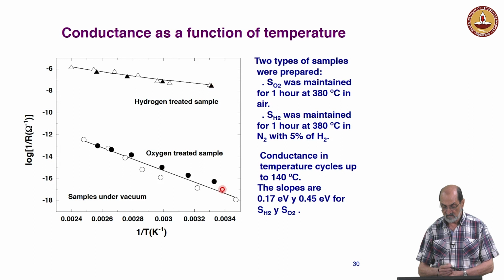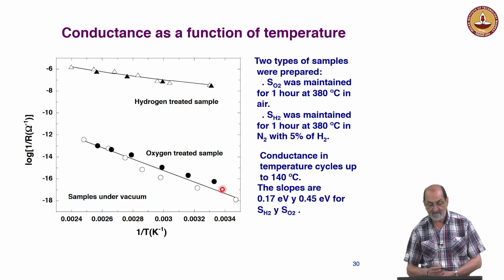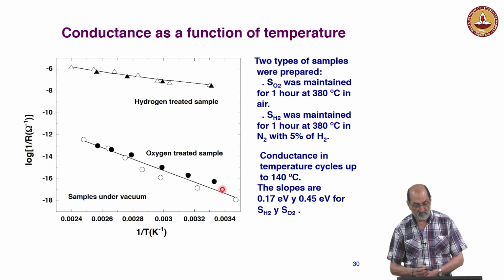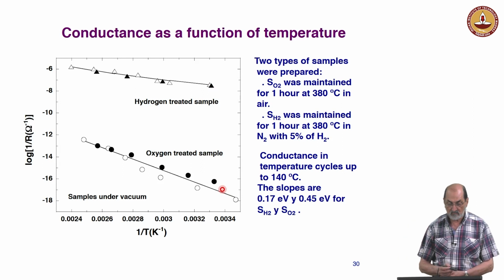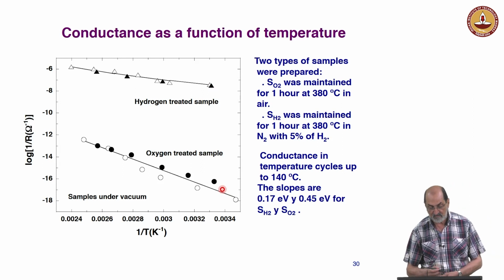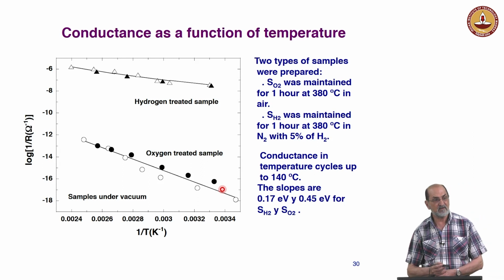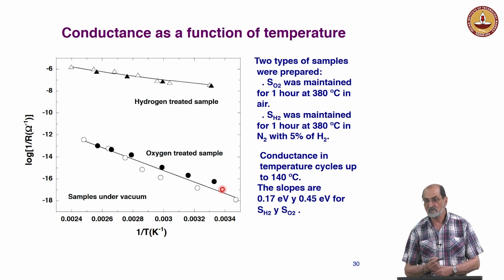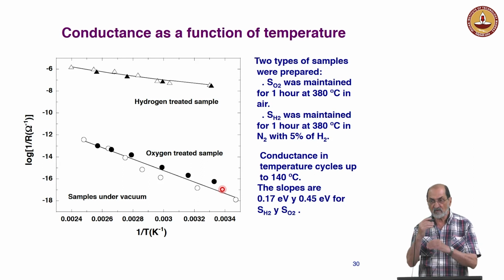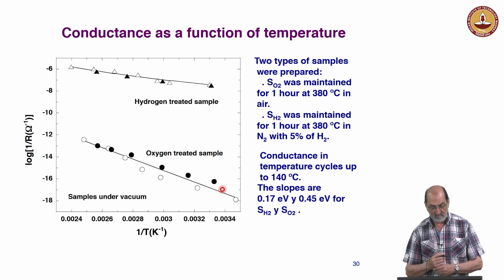So what would be the answer from the regular knowledge? Well, they would say, you treated the sample with hydrogen, and then you altered the surface, and now your Schottky barriers are smaller, and that's why the conductivity increases, because the intergranular barrier has lower height.